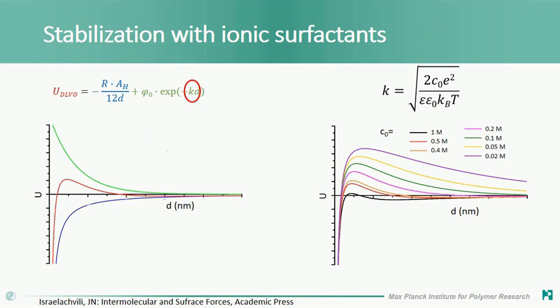And sometimes just using Milli-Q water from the machine might not be enough. It might be better to use a buffer solution to have reproducible results, because depending on exactly how much CO2 from the air dissolves in your water, you will have different amounts of charged species, and it will influence the colloidal stability, which will in turn influence the size of the nanodroplets that you form.